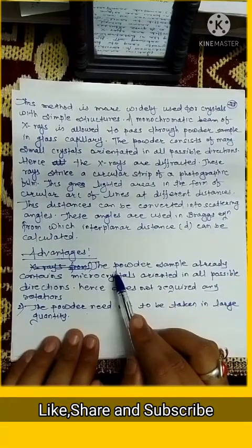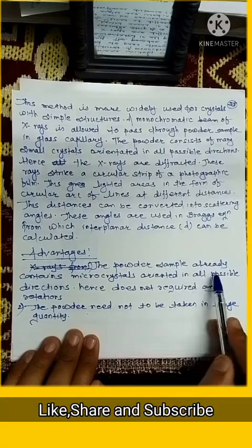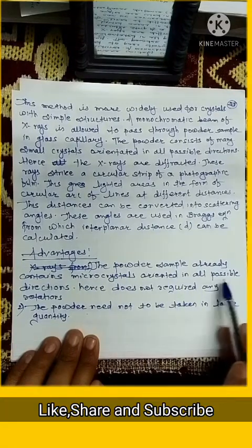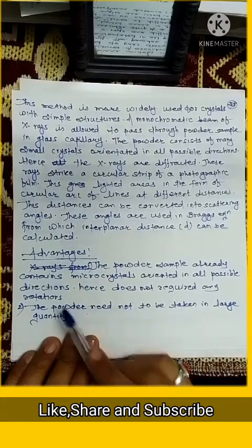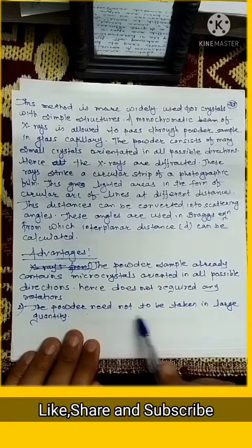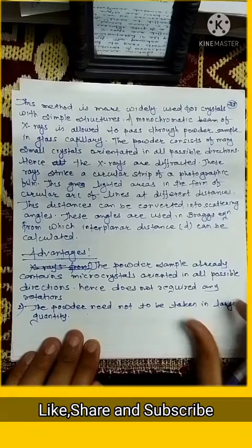The distance can be converted into scattering angle. These angles are used in Bragg's equation, from which interplanar distance d can be calculated. Now, what are the advantages of powder method? The powder sample already contains microcrystals oriented in all possible directions and does not require any rotation. The powder need not be taken in large quantity.